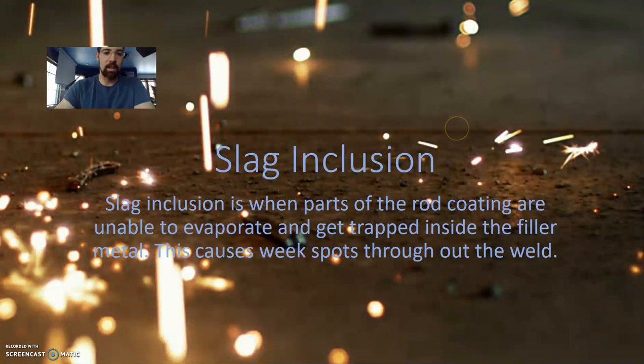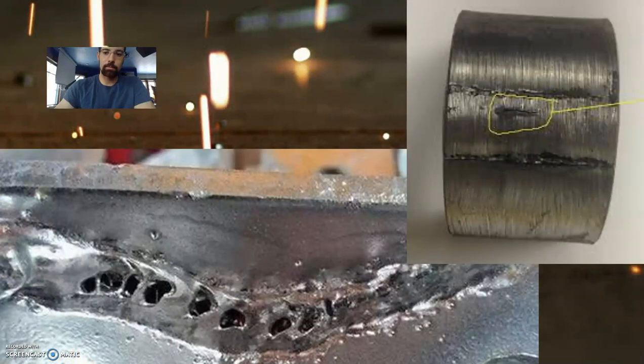All right, slag inclusion. This is when the coating from your rod or from your wire gets caught in your weld. It causes weak spots and a non-consistent weld. You can see pictures down below, got all these holes through your weld. That's all that slag that has been stuck in there. And up above, this is actually a bend test. The weld would look good from the surface, but when they bent it, you can see it pulled a crack here in the middle. That's that slag coming out.